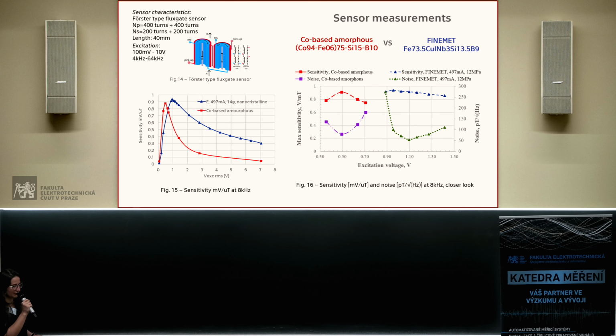So here is a comparison of results of the Finemet wire with the co-based amorphous wire. In terms of sensitivity, it is more or less the same, because you could see in figure 15 the red color stands for co-based amorphous, and you could see that sensitivity is just a bit lower, but it looks like there is a spike, and even if you slightly increase the excitation, it will drop much more rapidly than it does for nanocrystalline wire. So the characteristic for the nanocrystalline core is much flatter, which is better.